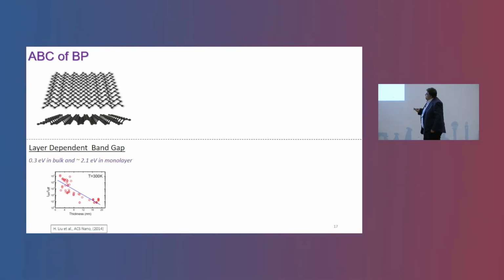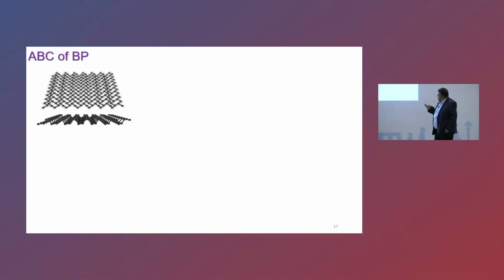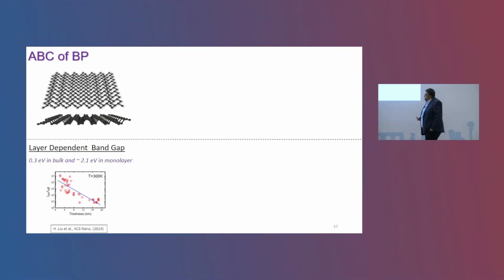The black phosphorus crystal structure basically has a puckered structure, with some edges terminated in the armchair direction and some edges terminated in the zigzag direction. This material has a layer-dependent band gap. In bulk, it has a band gap around 0.3 eV, and whenever you go to the monolayer, the band gap becomes 2.1 eV. So it's a nice semiconductor compared to graphene.